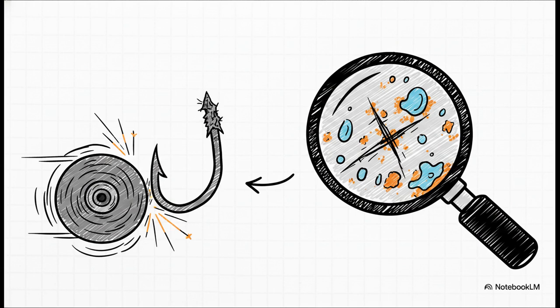Wait, grinding damages the hook? Are you saying the traditional sharpening method is actually weakening it? Yes, exactly. It can drop the tensile strength of the tip from 100,000 psi all the way down to just 35,000 psi. Plus, those little scratches become perfect microscopic pockets for aggressive saltwater corrosion.